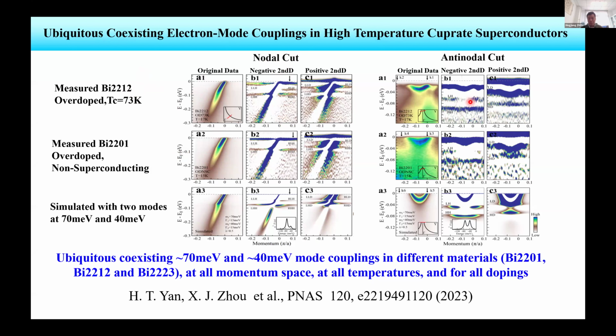Also, near the nodal region, you can see the electrons coupling with both the 70 meV and the 40 meV modes. That means the ubiquitous coexisting 70 meV and 40 meV mode couplings are observed in different materials, at all momentum space from the node direction to the antinode direction, and at all temperatures, above Tc and below Tc, and for all dopings. I think that's the new insight we obtained from the laser ARPES measurements: coexisting 70 meV and 40 meV electron-mode couplings in all the materials, at all temperatures and at all momentum space.